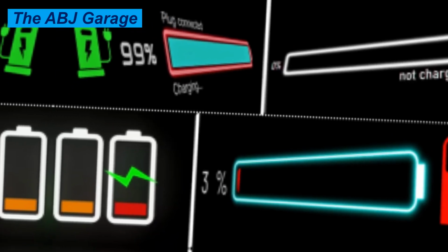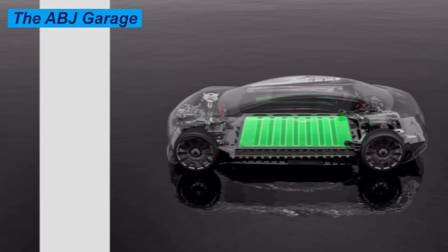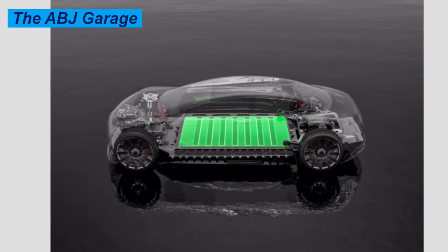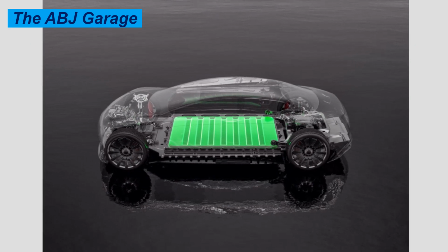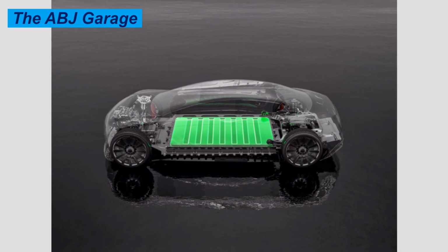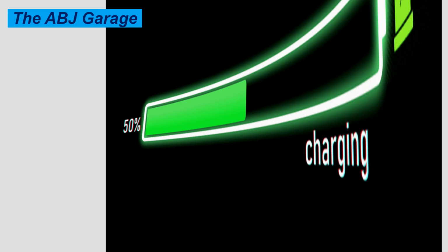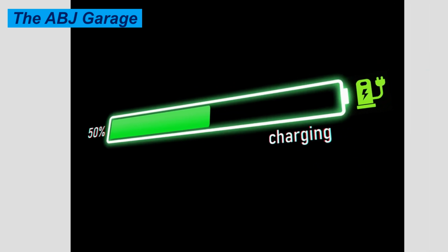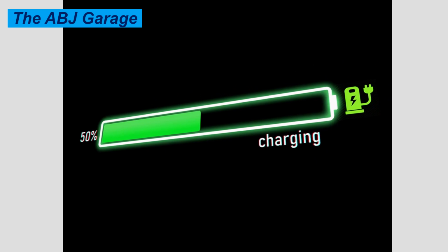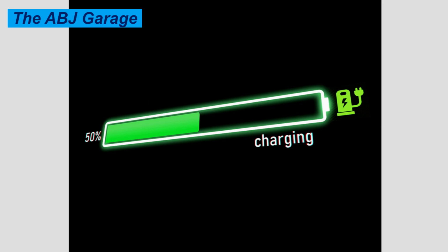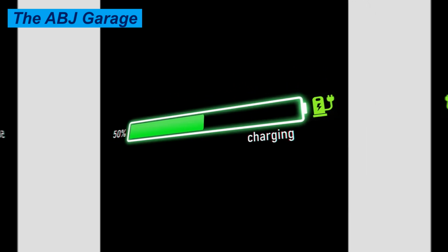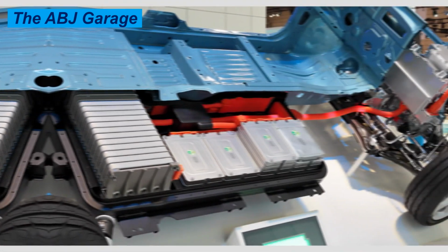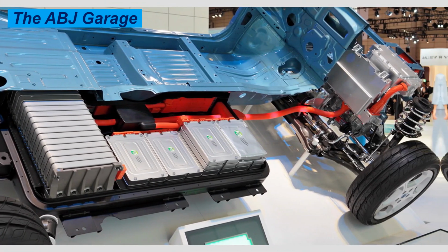Number four, ignoring extreme temperatures. Leaving the car unplugged for extended periods in very hot or freezing cold weather. So, what could be the problem? When it is extremely hot, heat causes chemical degradation and can prematurely reduce battery capacity. Cold doesn't cause permanent damage as quickly as heat, but it makes the battery inefficient and sluggish. More critically, if the battery is too cold and you try to fast charge, you can cause lithium plating, which is irreversible damage to the internal construction of the lithium-ion battery.